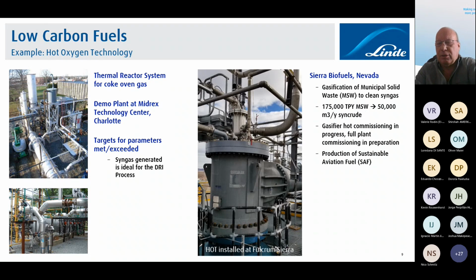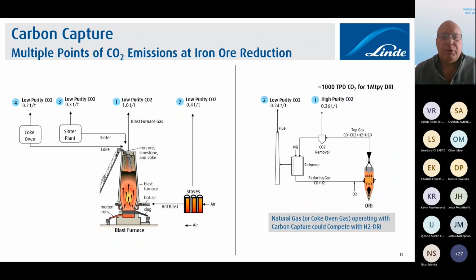And using waste plastics or municipal solid waste is a very nice way of creating, of course, a circular economy. Carbon capture is another piece in it, as I already mentioned, and using the iron and steel industry as an example, there are multiple points where we can also capture CO2 from the main sources there. And that goes both for the dominating blast furnace-based route and for the DRI-based route using natural gas as a reductant. And we should keep in mind that transporting CO2 is way easier than transporting hydrogen. So that could definitely be a complementary solution here.